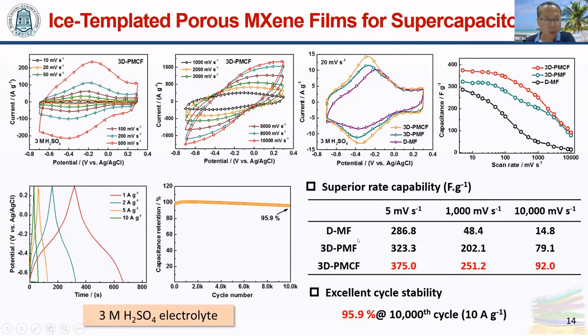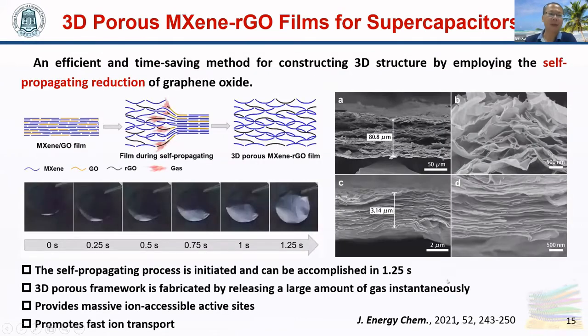Due to the open structure, the increased active surface sites, and the good transportation of the ions, these materials show a very high capacitance and very good cycle stability in supercapacitors. In addition, we also provide an efficient and time-saving method for constructing 3D structure by employing the self-propagating reduction of